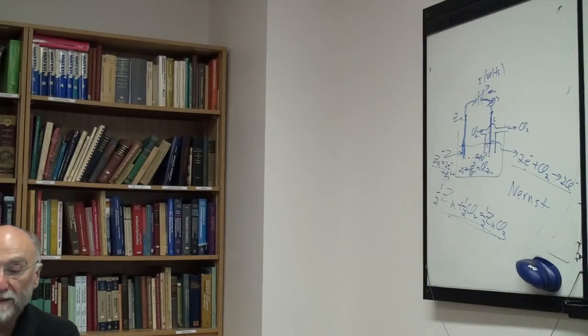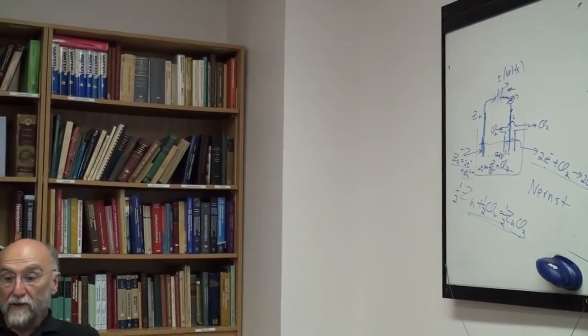Measuring enthalpy change. I said the enthalpy change can be measured directly by calorimetry. We talked about a bomb calorimeter. You actually run the reaction from reactants to products, and you measure the heat in the calorimeter. That was a bomb calorimeter. If you want to measure a heat of mixing of two liquids, you take A and B in a calorimeter, you mix them, and you measure the heat that comes off. If you want to measure the enthalpy change for a reaction, you carry out the reaction in the calorimeter and you measure the heat. There's another way of doing it.